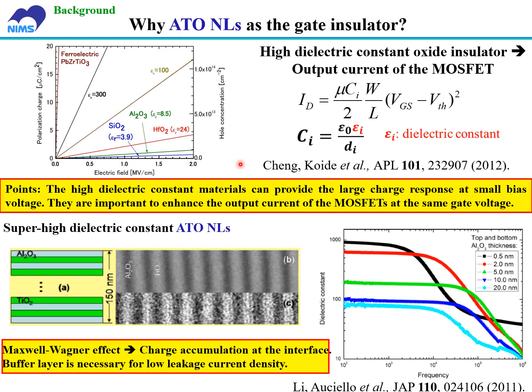The first question is why ATO nanolaminates as the gate insulator. This figure shows the polarization and the hole accumulation as a function of electrical field. High dielectric constant materials can provide a large charge response at a small bias voltage. This equation shows the relationship between the output current of the MOSFETs and the capacitance and the high dielectric constant. Higher dielectric constant materials are important to enhance the output current of the MOSFET at the same gate voltage.